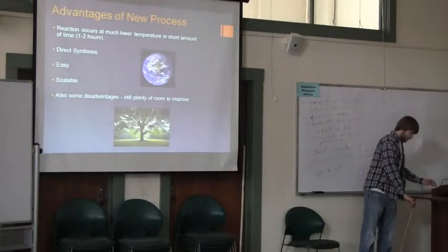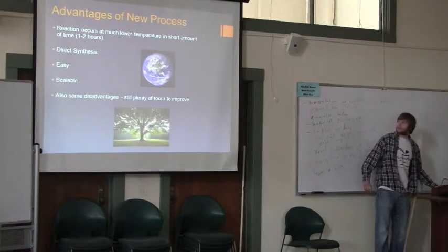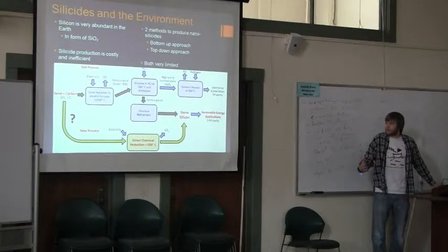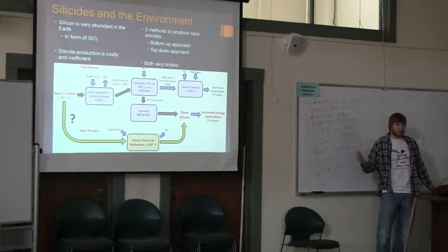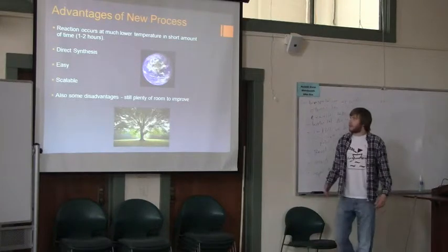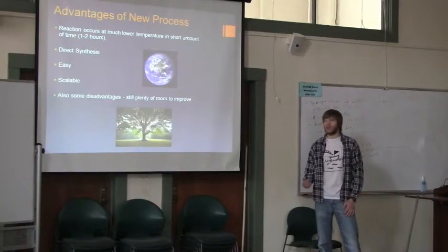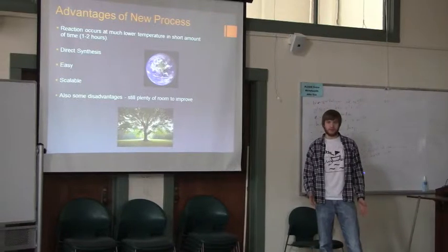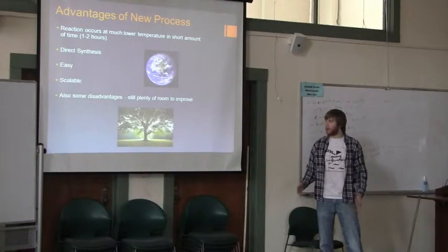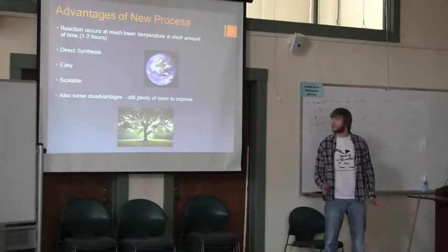So let's talk about some of the advantages of what we've worked on. If we go back just real quick to this, the old method of producing, or not necessarily the old method, but the way you would do it previously, involved this lengthy refinement step that involved high temperature and ended up with a low volume product. Our method accomplishes it at a much lower temperature, around 650 degrees Celsius. That's about 1,000 degrees cooler. Lower temperatures mean a lot lower energy. And then in 1 to 2 hours, it's really easy, it's quick. And it accomplishes it in only 2 steps instead of the whole refinement process. So all of these factors combine to really increase the sustainability of this process compared to previous methods.